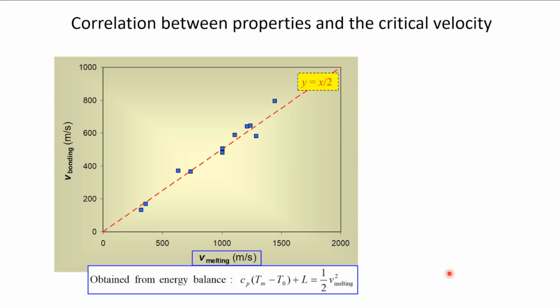So I didn't give up on this correlation study. I tried to come up with a kind of combined material property and plot critical velocity as a function of that. So this is the combined material property. This is obtained from an energy balance, assuming that if you hit the particle on a rigid surface and that results in melting, how would the kinetic energy correlate with the thermal properties? And I ended up with this. So you see that you will need half of the velocity, or a quarter of the kinetic energy that you will require for complete melting, in order to have bonding.